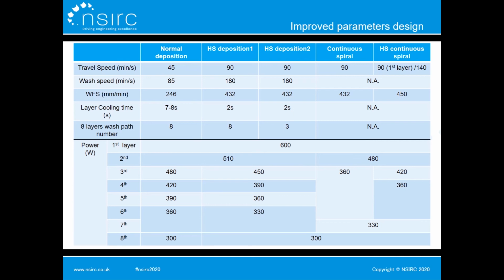In the high-speed deposition 1 and 2, I increased the travel speeds of deposition and wash pass. Meanwhile, the cooling time of each layer is also reduced. After the trials, to get a faster processing procedure, the wash pass and cooling time were removed. So in the continuous spiral method, the wire will keep feeding from beginning to end, and the deposition route is like a spiral from the base substrate to the cylinder top. Then I increased the deposition speed to complete the final design of high-speed spiral deposition.